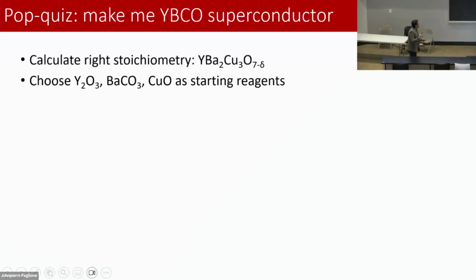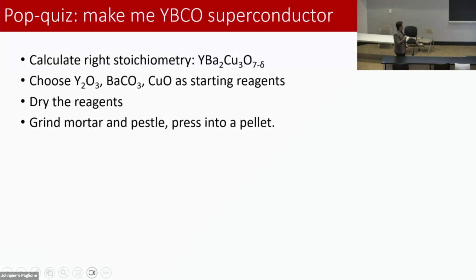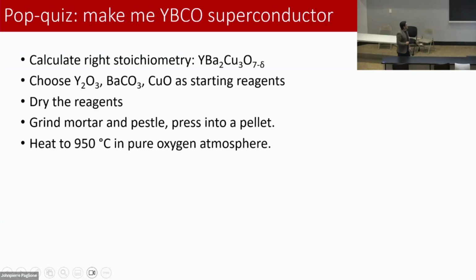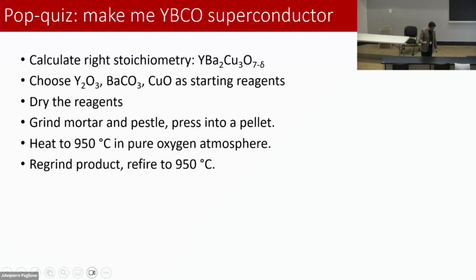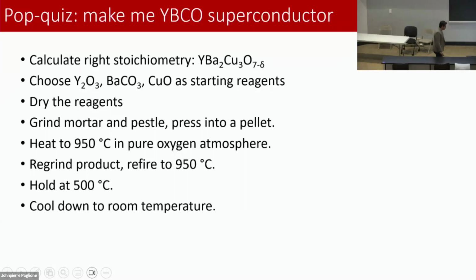So these are common starting reagents. Dry them, right? Make sure that they are what they are. Grind in a mortar and pestle. Do it really, really well. Put some elbow grease into it. Press into a pellet. Heat at 950 in a pure oxygen atmosphere. Regrind, refire, and then hold at 500. And then cool down to room temperature. This is a common recipe.